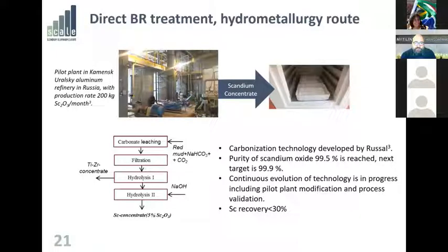This is a technology that has been developed by Rusal. It uses a mixture of sodium carbonate and CO2 to leach out scandium from the bauxite residue. It then proceeds to hydrolysis steps to remove some impurities and ends up with a concentrate of about 5% scandium oxide. The recovery of scandium from this bauxite residue is less than 30%, but it is a very attractive process in terms of capex and opex and simplicity.